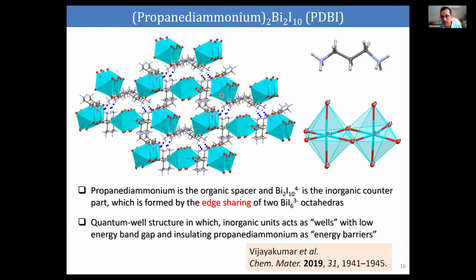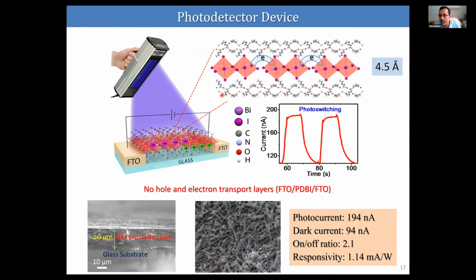In addition to that, the distance between the octahedron is very small, 4.5 angstrom. And because of that, the charge hopping is very easy in this material, and we were able to develop relatively efficient photodetector devices with our material. And interestingly, we didn't need to use any hole or electron transport layers, because our material itself is transporting the charges. And we try to understand the next.